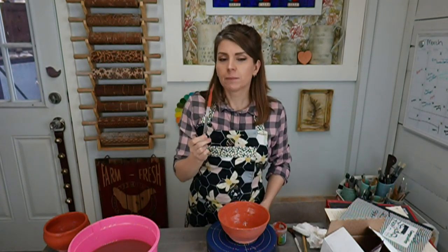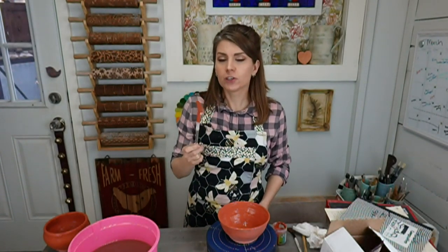I'm not sure I understand offset or how to do it, but you might not need it, Barbara. So an offset is when you have a computerized kiln, and when you fire it the first time doing your kiln firing tests, it fires too hot. So you do a cone 5 test, but it's getting to 5.5, and that's too hot. So you need to bring it back down, and it just tells the computer inside that instead of cone 5 being 2167, if you do a 30-degree negative cone offset, it thinks that cone 5 is 2137. So it brings it down 30 degrees.